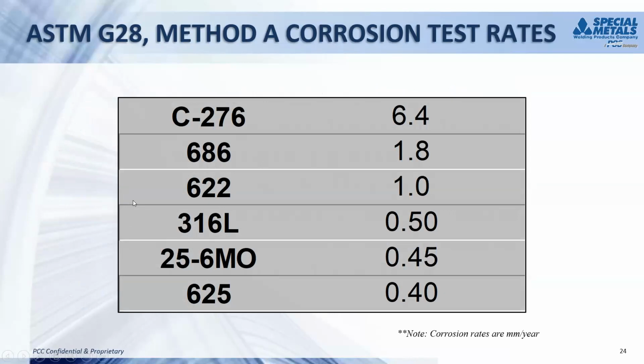The corrosion resistant alloys and stainless steels have to be in the right condition to provide their optimum corrosion resistance. They have to be annealed properly, and they have to be cooled properly after annealing. The G28A test is designed to verify that products have been properly heat treated. And when you're testing material, you compare the rate you get to the base rate for the alloy. And if it matches, you know that it's been properly heat treated. But if you try to compare alloys to each other, you'll get erroneous results.